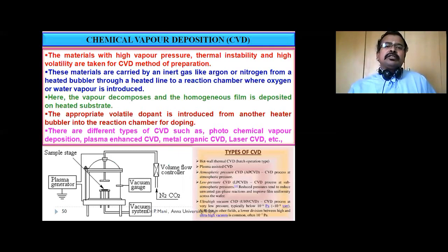Chemical vapor deposition, the famous CVD technique. Here the materials with high vapor pressure, thermal instability, and high volatility are taken for the CVD method for preparation. These materials are carried by an inert gas like argon or nitrogen from a heated bubbler through a heated line to a reaction chamber where oxygen or water vapor is introduced. The vapor decomposes and the homogeneous film is deposited on the heated substrate.